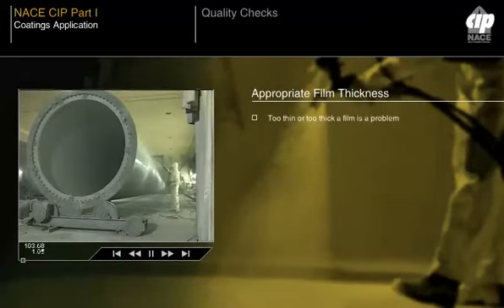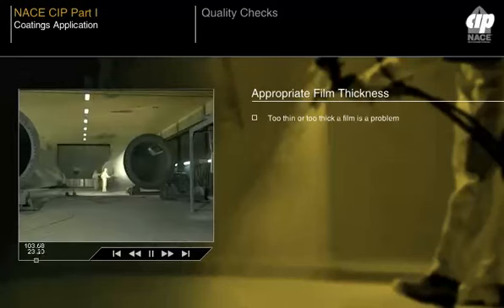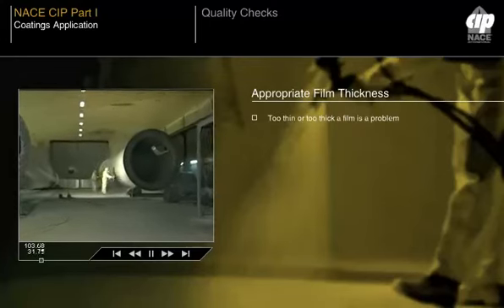If coating is too thin, pinpoint corrosion can occur. If too thick, the coating may crack. High film thickness is likely to be a bigger problem than low film thickness, due to development of stress during the coating drying and curing cycle, and is more difficult to correct than low DFT. Over-thick coatings may retain solvent, leading to problems with cure and possibly to blistering in extreme cases.